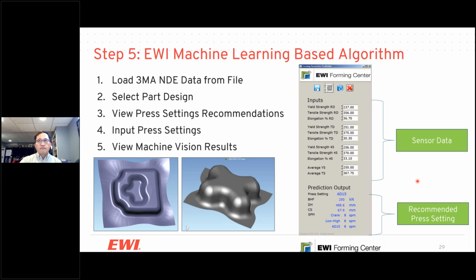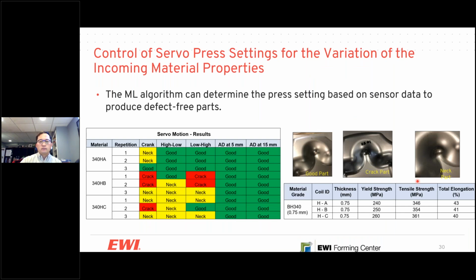But if the press manufacturer down the road agrees to allow our algorithm to communicate directly with the press HMI panel, the PLC board, this is also technically possible: our control algorithm could communicate directly with the press control. This is an example of a study for high strength material, as well as some of the bake hardening 340 steel. 340 bake hardening steel is commonly used for the closure panels of automotive vehicles. We tested 3 different batches of material from 3 different batches of coil.